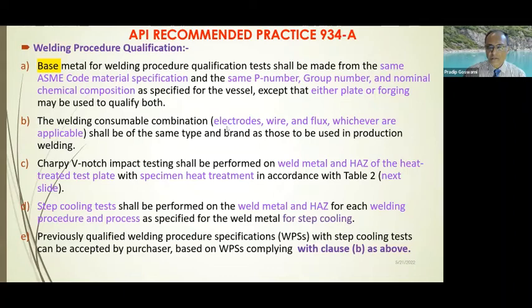Welding consumables for each welding combination, where flux and wire are used, shall be the same type and brand as those used in the production welding. That means you just stick to one brand, one specific lot, one specific heat number, or one specific wire and flux combination for these reactors. They are very, very specific and very stringent about this. The impact test is definitely a mandatory requirement. The step cooling test is a requirement for each weld procedure and process specified, and every weld has to pass.